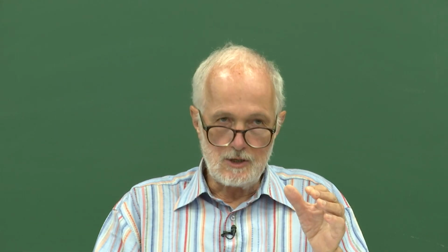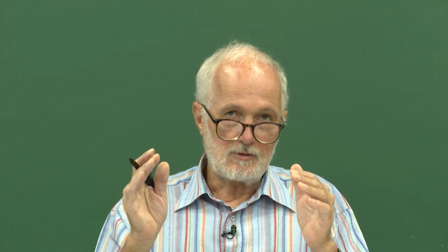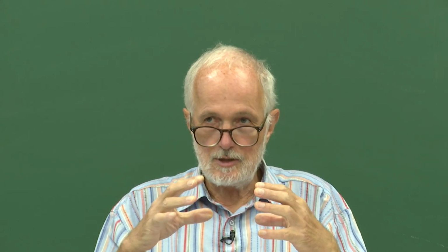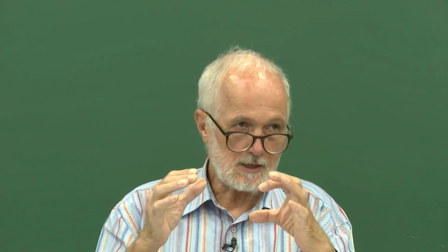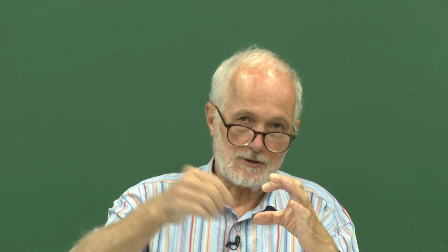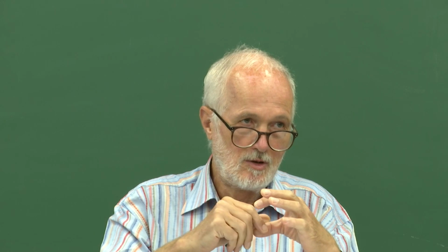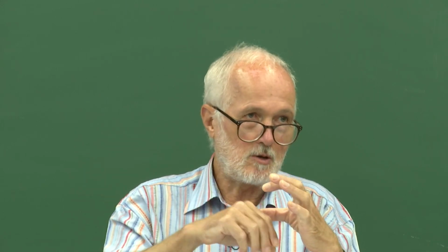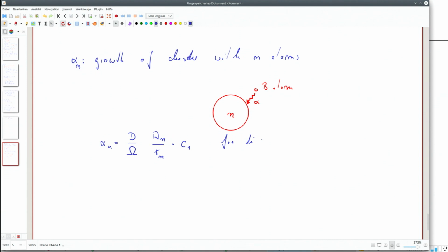It depends whether you consider a diffusion limited or an aggregation limited case. Both is possible, but typically in metals we have this diffusion limited situation, so it takes time to transport B atoms to this cluster. And the aggregation to the existing cluster is very simple. If you have, for example, an oxidation process, it can be much more complicated to put this additional atom into this existing interface, and it's interface limited or aggregation limited. So this is for diffusion limited growth. So this is simple.